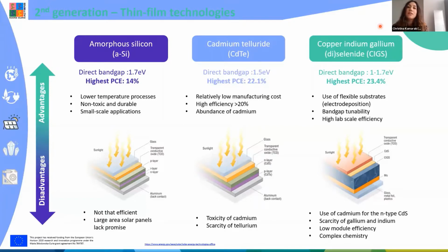This type of solar cell has the unique property of a tunable bandgap because we can play around with the composition and the ratios between these four materials. And also they can be fabricated on flexible substrates using the electrodeposition method. However, the scarcity of gallium and indium and the use of cadmium sulfide as a selective layer is again prohibiting. Also, these nice efficiencies of up to 23% cannot be replicated in large area modules, which is again a drawback.